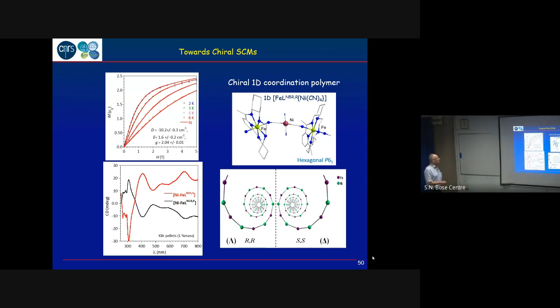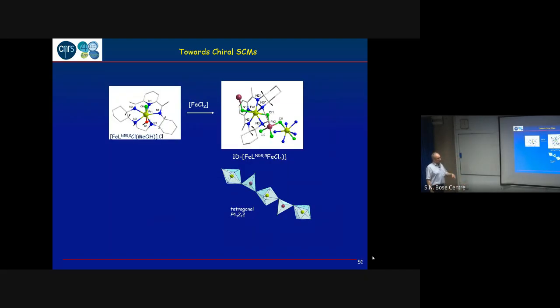So we can also investigate the magnetic properties. We do that just to have an idea of the anisotropy. So this is the anisotropy of the iron center, and again, we just get what we expect. In the previous example, the nickel was diamagnetic. So what we try to do is also play with exchange interaction and with paramagnetic species. I would like to show only one example here. This piece is a little bit more complex, but it was a little bit funny because we did not expect what I'm going to show.